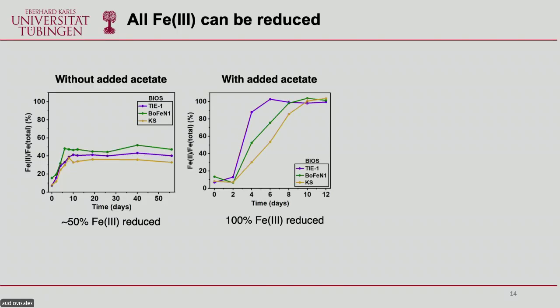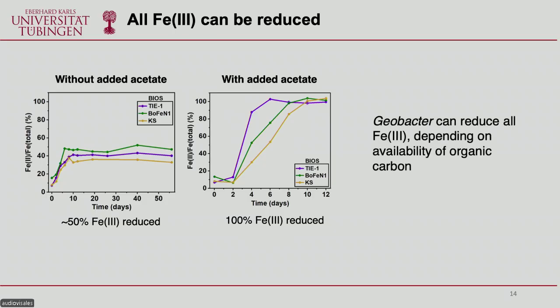And if we add acetate, which is a really easily degradable organic carbon, then we see actually that within 10 days, about 100% of the iron 3 can be reduced. So these biogenic iron oxyhydroxides can be easily transformed by microbial iron reduction. And the extent of the transformation depends on the availability of organic carbon in the environment.